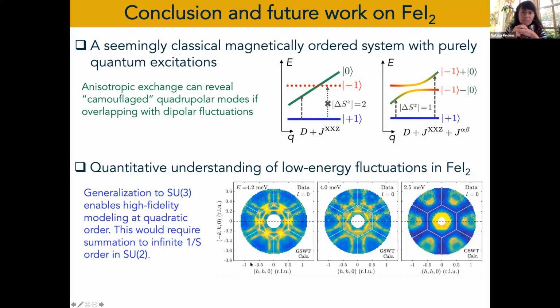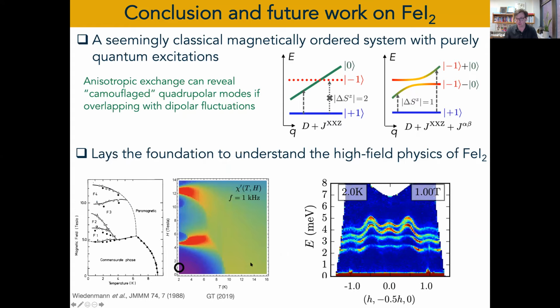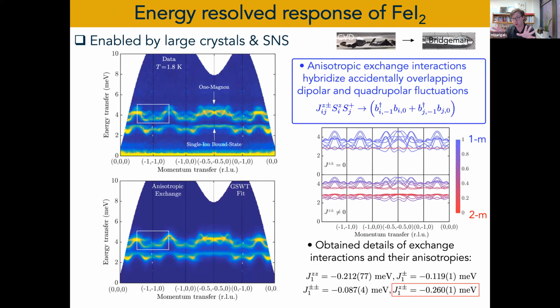Yeah, so I'm going to have to plead the fifth here a little bit. This is definitely where we are going. And in fact, when we apply the magnetic field, it's pretty clear that some of the decay conditions you might expect to happen, these kinematic conditions, in fact become fulfilled. So in these magnetic field measurements we are actually tracking for such effects. What we know is that in zero Tesla, which is the bulk of the data I showed here, as far as we can tell, the excitations are completely sharp.